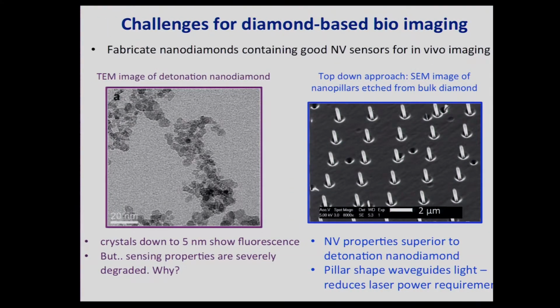Another challenge, as I mentioned, is if one wants to really do in vivo imaging, you want to be able to make small nanodiamonds and inject them into cells. There have been demonstrations of 5 nanometer nanodiamonds with fluorescent defects inside. These are traditionally produced in a rather violent way. It's detonation nanodiamond. They're basically an afterproduct of some explosions. But they can be made quite small, and they can be sorted to get reproducibly small nanoparticles. This is a TEM image showing a bunch of 5 nanometer-ish size particles.